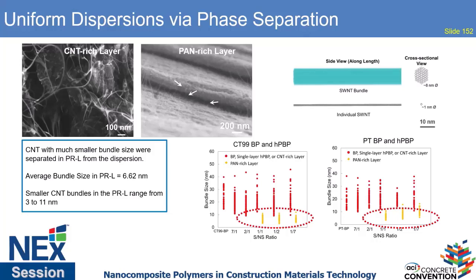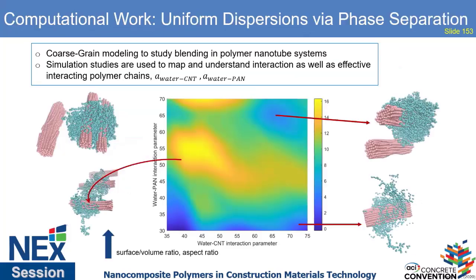As the polymer forms a coil or a solvated coil in a different solvent system, it has a certain amount of free volume, and it can actually capture or wrap itself around the nanomaterial. So if we do that in a very controlled way, we essentially can pull out the nanotube bundles that are more easy to interact with for that particular polymer. People have shown this with DNA, for example. We're essentially doing this with different polymer, long chain polymers.